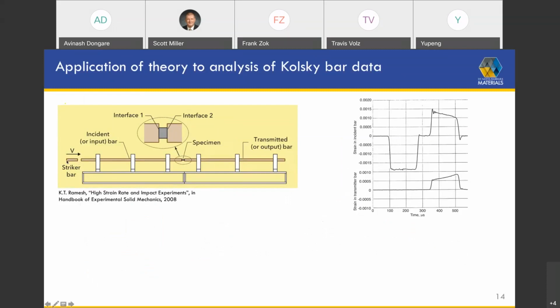So think about the physics here, the mechanics. You have a striker bar, it hits this interface here. You have a stress pulse in the striker that goes from the interface back into the striker, and you have a pulse going into the incident bar. The pulse in the striker reflects off the back face, comes back as a tensile wave, moves forward, and at